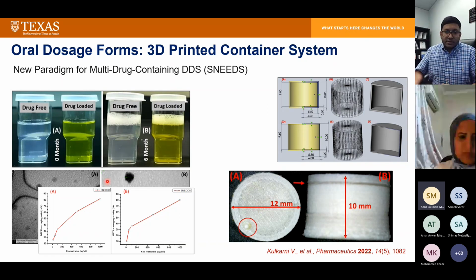And we did some physicochemical characterization of the blank and drug loaded SNAPs, and what we found, the antioxidant level was dependent on the formulation composition, and the effective, like kind of like 50% effectiveness was achieved at about 330 to 393 microgram per milliliter concentration for both SNAPs formulation.